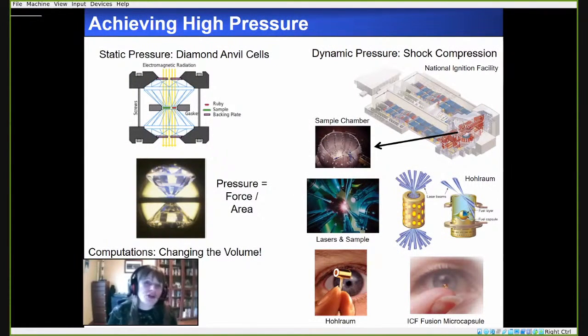So how does one achieve high pressure? In experiments, one way to do this is by using diamond anvil cells, shown here, and that is able to produce pressures that are static. So pressure is force over area. Therefore, if you have a diamond anvil cell where the tip is very small, you're going to be able to get higher pressures. Using conventional diamond anvil cells, the pressures that one can realize are on the order of 300 gigapascals. However, there have been new technologies made available where you shape the tip of the diamond anvil cell into a toroidal shape. And these types of techniques can reach even higher pressures on the order of 500 gigapascals.